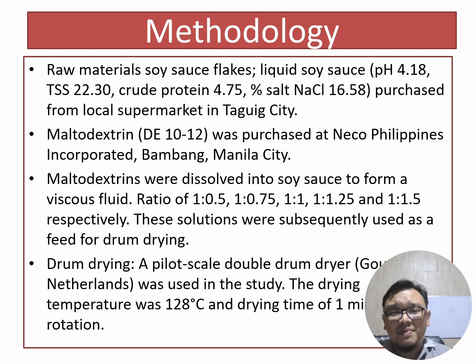Okay, so for the methodology, we utilized the soy sauce and added maltodextrin at certain percentages. A ratio of 1 to 0.5, one ratio of soy sauce to 0.5 ratio of maltodextrin. Then 1 to 0.75, 1 to 1, 1 to 1.25, and 1 to 1.5. As we can see, we have established different ratios to determine the effect of maltodextrin.